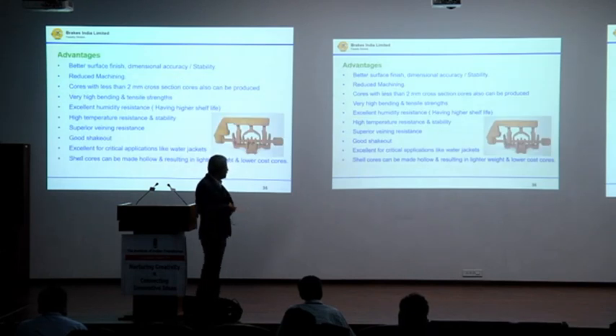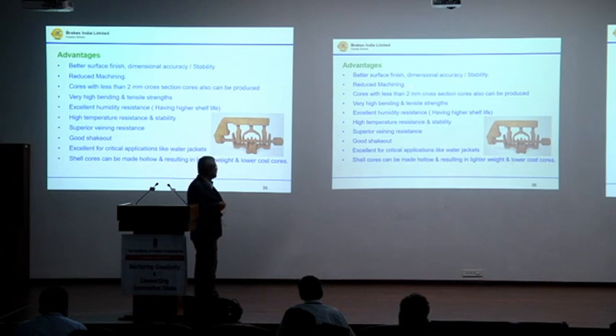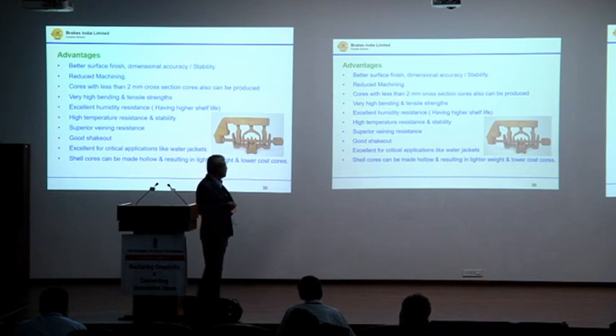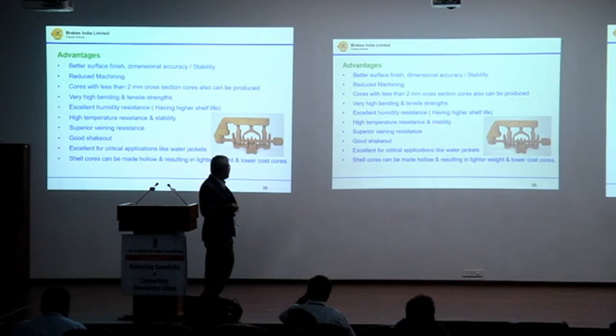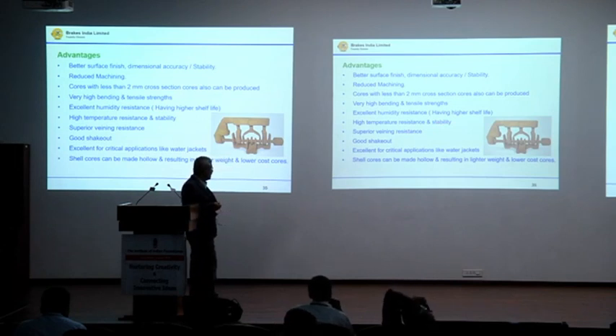This is the advantage of shell cores: better surface finish, dimensional accuracy, and reduced machining stock you can maintain. Cores with less than 2 mm core section thickness can also be made with this process. It has very high bending and tensile strength, excellent humidity resistance, higher shelf life, high temperature resistance and stability, superior veining resistance, good shakeout, and is excellent for critical applications like water jackets. Shell cores can be made hollow, resulting in lighter weight and lower cost of cores.